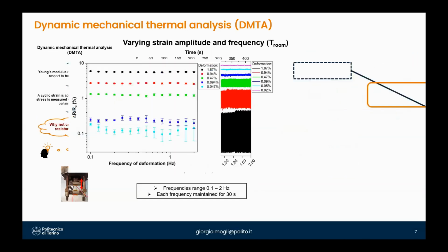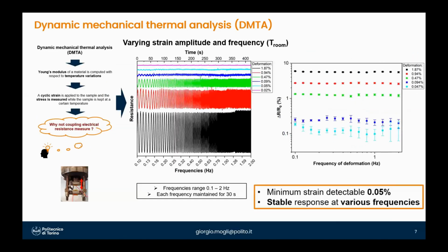fluctuations. And moreover, the average values of the variation of the resistance for each frequency of the deformation applied were computed, showing that for each deformation investigated, they are quite stable.